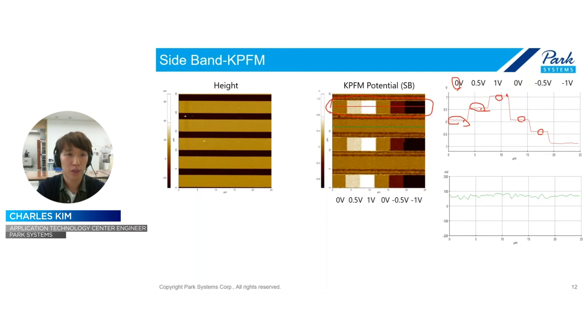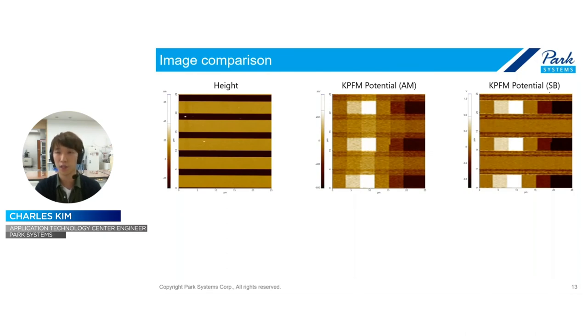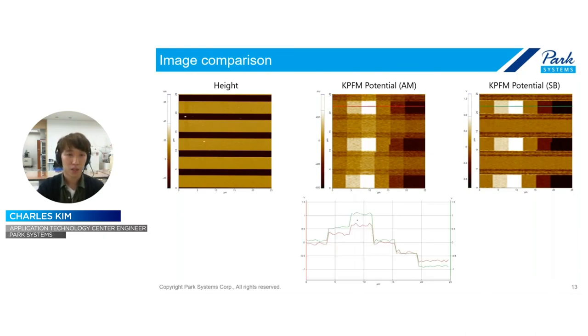And also when I draw the line in the grounded line, there is no artifact from the averaging from the near electrode. Even though they are very close, there is no change in the potential. So when I compare the AM and the sideband KPFM, the sideband has a much closer and much more exact result compared to the AM. And also when you compare this line and this line, you can see the sideband has a very flat and same value on the ground line.